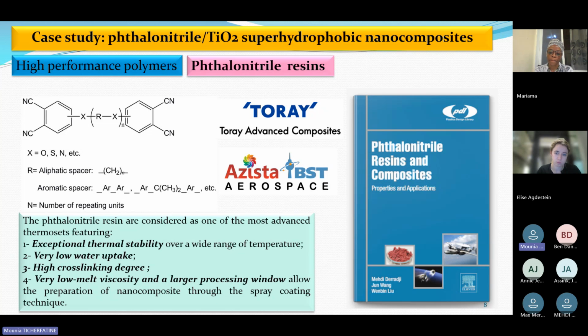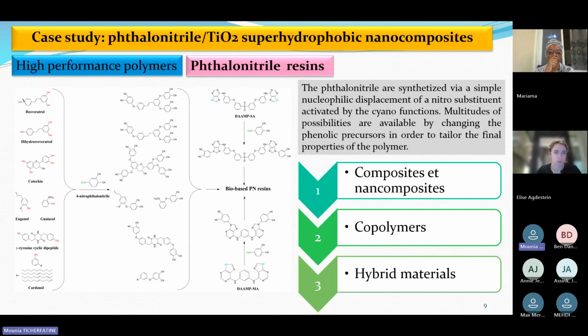Here, the phthalonitriles are synthesized by a simple nucleophilic displacement of a nitro substituent activated by the cyano functions. A multitude of possibilities are available by changing the phenolic precursors in order to tailor the final properties of the polymer. Meanwhile, the use of environmentally friendly precursors like eugenol, cardanol, among others, allows the development of biopolymers displaying some of the same or better performances than their petroleum-based counterparts.